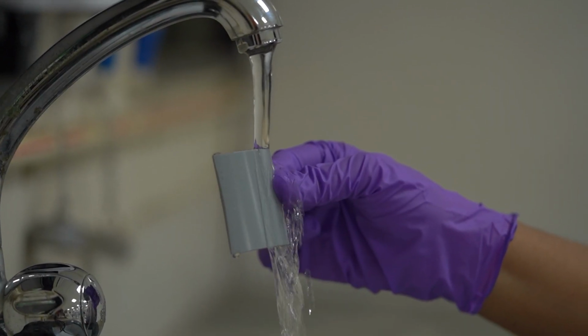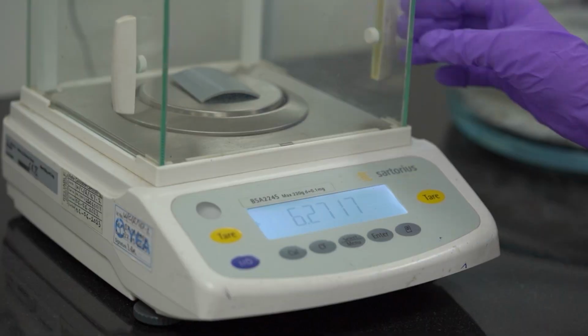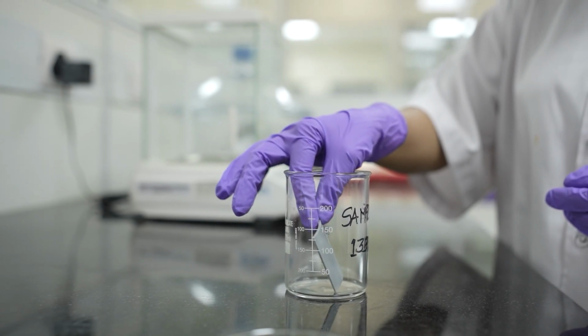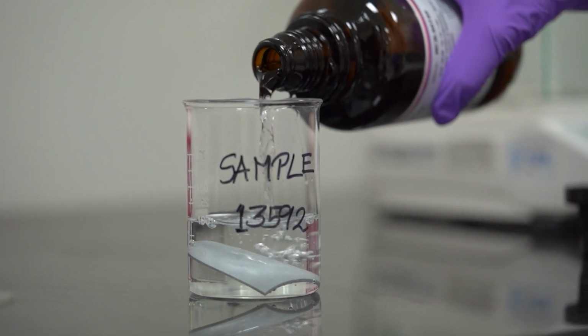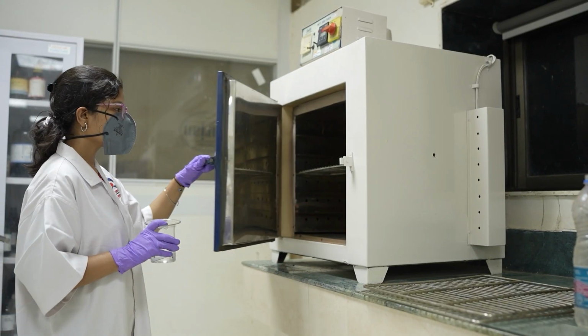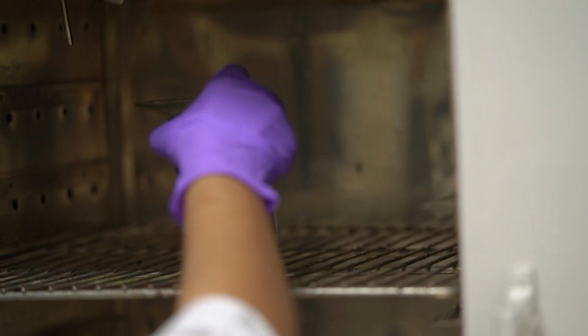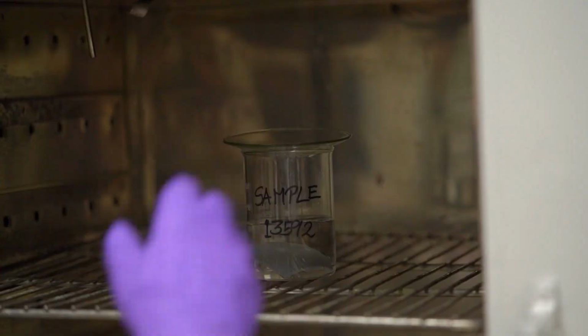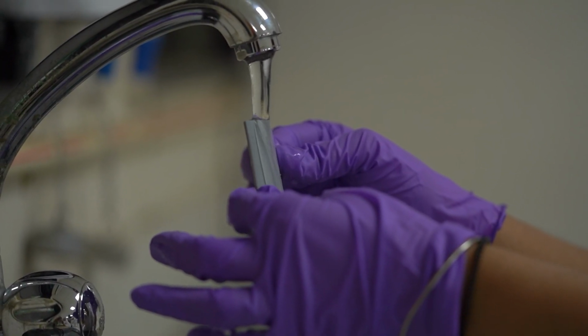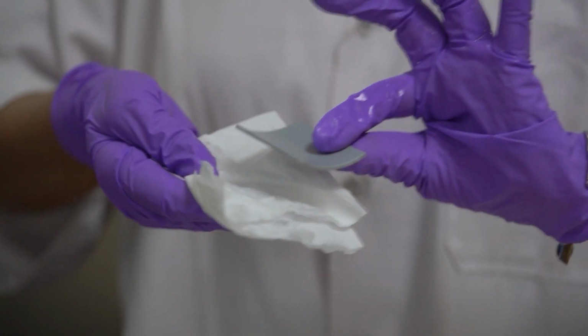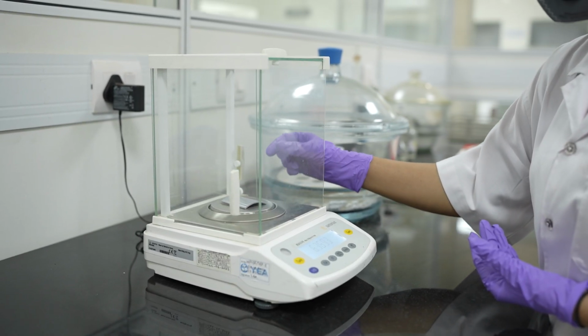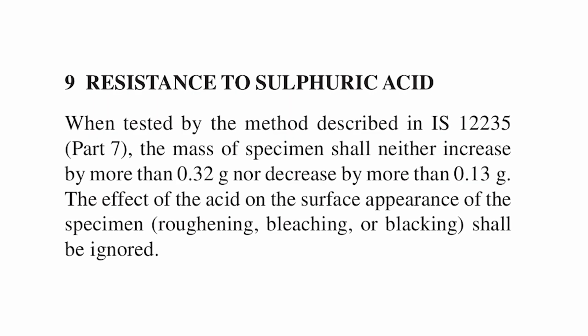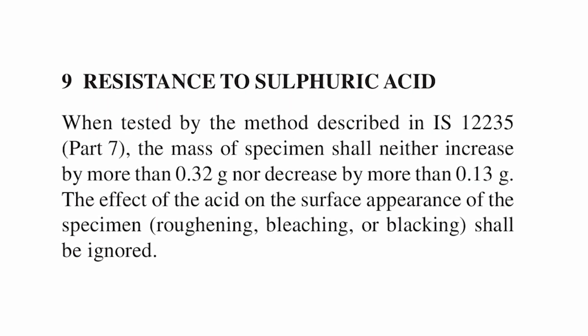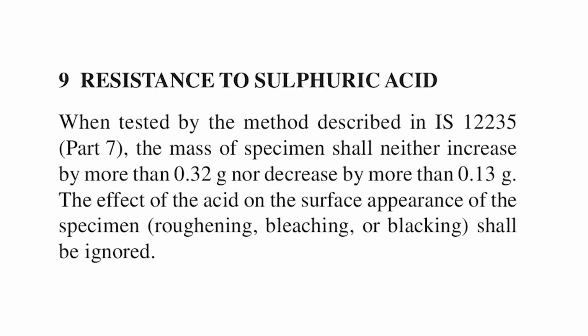The test specimen is cleaned, dried, and its initial weight is recorded. Then it is immersed in 93 plus minus 0.5 sulfuric acid solution and kept in the oven for 14 days at 55 plus minus 2 degrees Celsius. After 14 days of heating, the specimen is rinsed under running water, dried, and the weight of the sample noted. The final weight of the specimen shall neither increase by more than 0.32 gram nor decrease by more than 0.13 gram. The next test is resistance to external blows at 0 degrees Celsius.